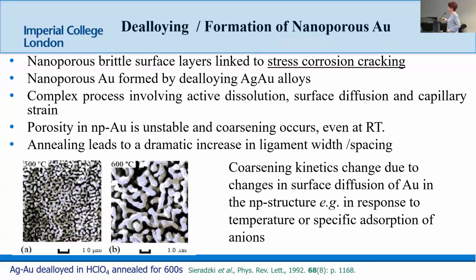A lot of work was started here and then, at Brookhaven, Newman and Sieradzki tried to understand particular types of stress corrosion cracking where you would have brittle failure in materials that were supposed to be ductile. So they developed the film-induced cleavage model, which says you've got a ductile material, but a brittle surface layer, caused by these electrochemical processes that form nanoporous structures on the surface.